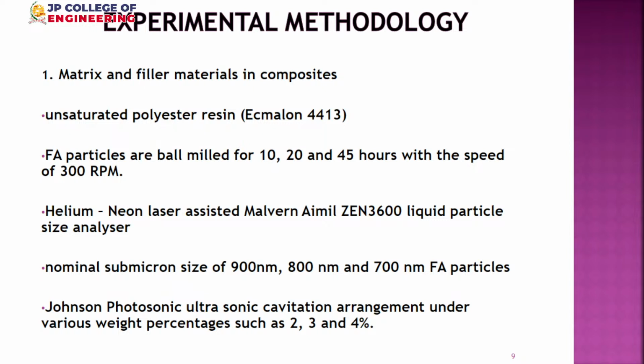The matrix we studied is polyester resin, and we prepared the fly ash particle. The fly ash received from our thermal power plant is coarse in size and has many different impurities. So you have to grade them and then size them in the required way. We obtained that by doing high-speed ball milling at different durations to identify what size we are getting. Then the particle sizes were analyzed using a particle size analyzer. From our analysis, we selected 3 different sizes of the FA particle, ranging from 900 nanometer to 700 nanometer.